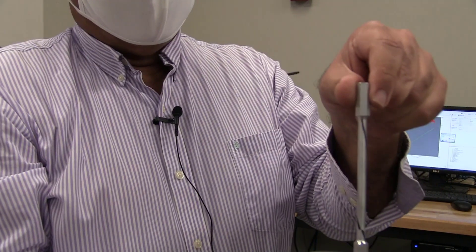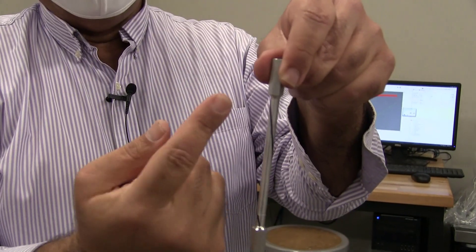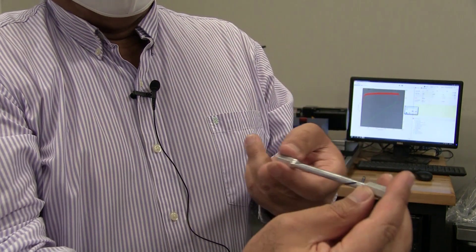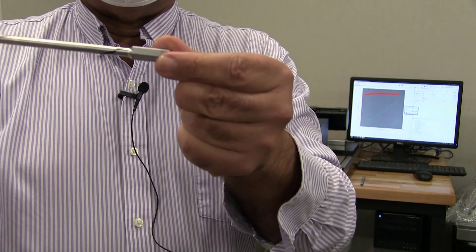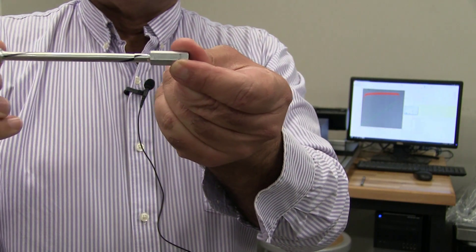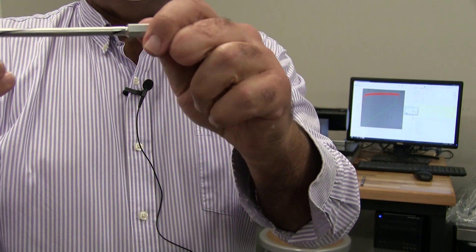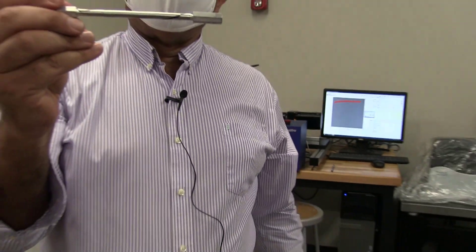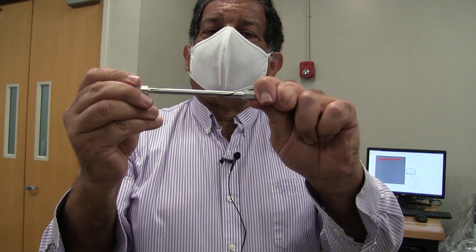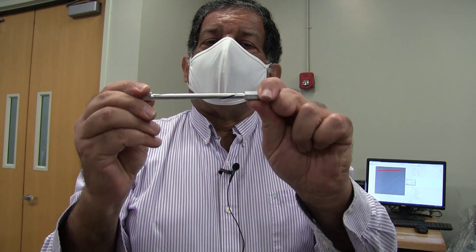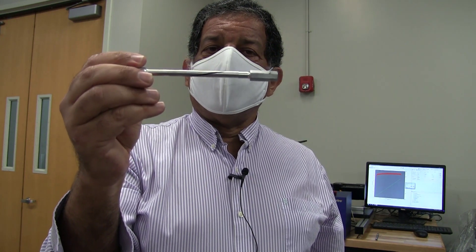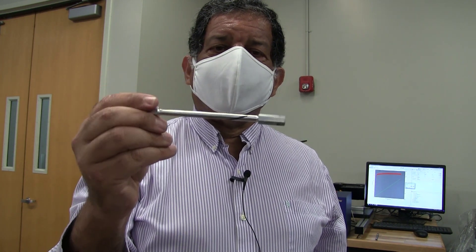And you'll see some really cool stuff here. First of all, you notice this used to be a straight black line and you notice the helix going all the way around the specimen. Secondly, you notice the shear fracture over here. You can see the discontinuity in the straight line where there's a shear fracture. Also, you notice the cross section of the specimen does not change where it fractures because this is a shear mode of failure rather than a tensile mode. Think about the implications of that for why this specimen has got so much ductility as compared to the tensile specimen.